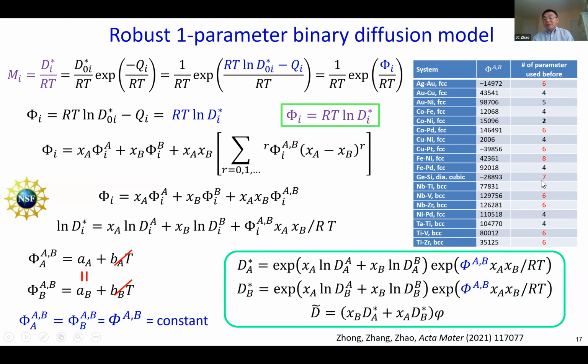In comparison, some of the literature mobility assessments use up to 8 parameters for a binary system. A lot of them use 6 in the 18 systems. Half of them use up to 6 parameters. And you really don't need that many parameters.